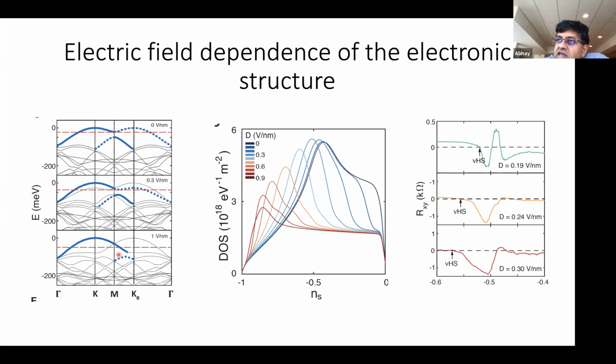Now, one of the issues with many of these materials, these dichalcogenides, is that the spin is on the transition metal, and so the out-of-plane exchange is actually quite small. Right? To make it care about what's on top, you have to increase that out-of-plane exchange. So that still needs some work. I see. Yeah. Thank you.